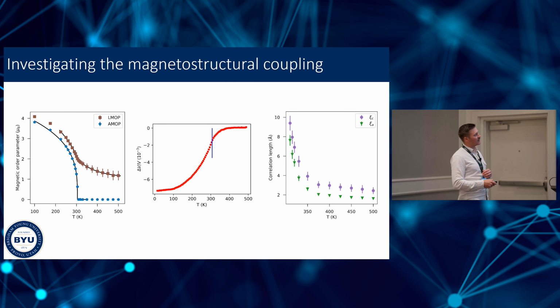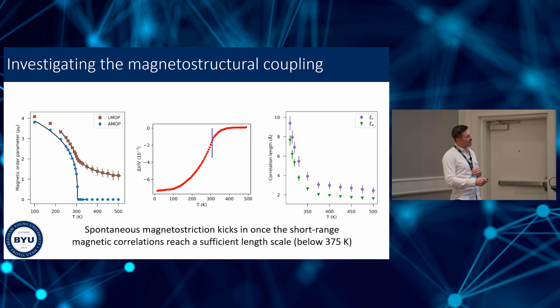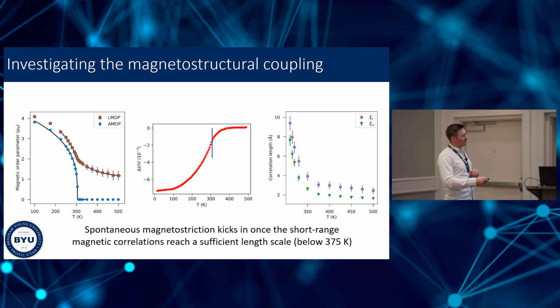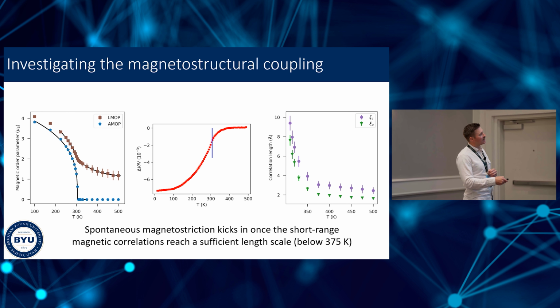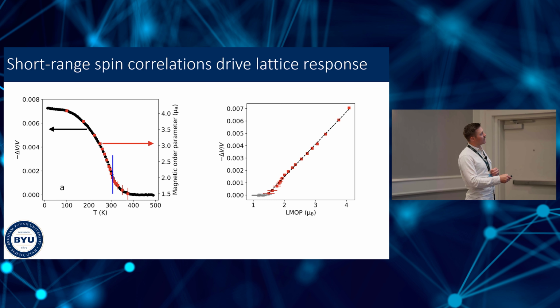What's maybe more interesting to me is to compare more quantitatively the information about the local magnetic structure that we have from our magnetic PDF analysis. Here's the local magnetic order parameter, LMOP, okay, it's the acronym for that. Here's the correlation length. Compare these local magnetic features with this average structure behavior of the unit cell volume, and they actually line up remarkably well. So I'm showing you here on the left vertical axis the volume change. I've actually made it positive just for ease of comparison. And on the right vertical axis, I'm showing the local magnetic order parameter. They lie right on top of each other.